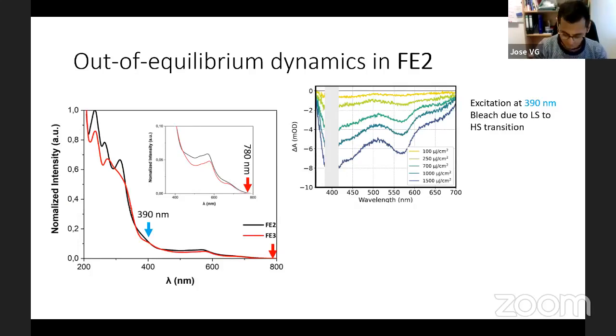So we use optical transient absorption in solution, of course, to track the low spin to high spin transition. When a spin crossover passes from low spin to high spin, there is a bleaching, especially around 400 nanometers, which is observable, for example, here in this slide. So if the material is having a transition at 390 and 780, we will be observing that in the optical transient absorption spectra, right?